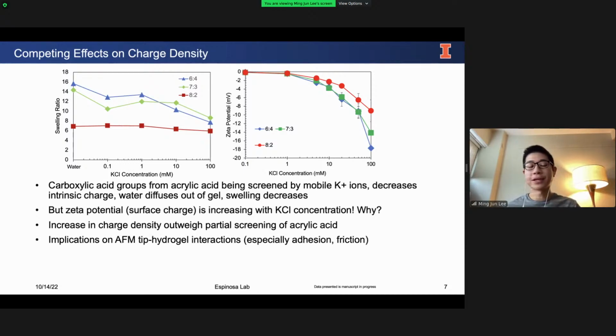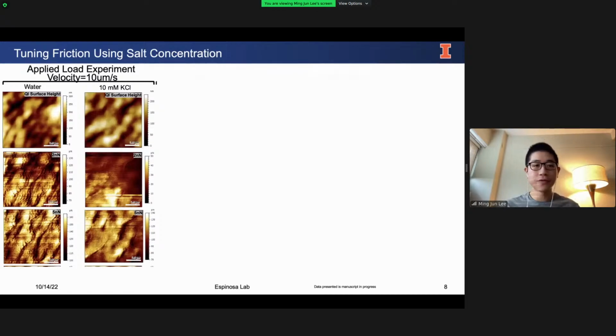This has implications on the interactions between the AFM tip, which is the method I'm using to measure these hydrogels, as well as the hydrogel surface. And this would especially affect the adhesion and friction data that we see in the previous and also the following slides to come. Now I'd like to move on to the friction experiments using different concentrations of salt solution.